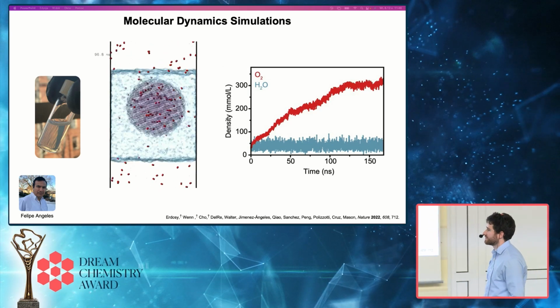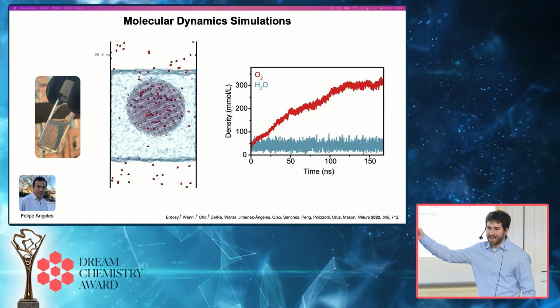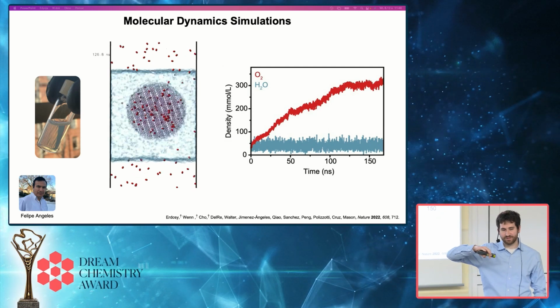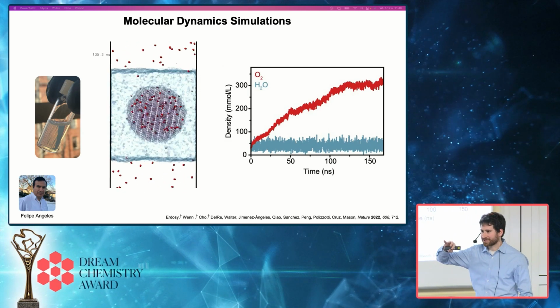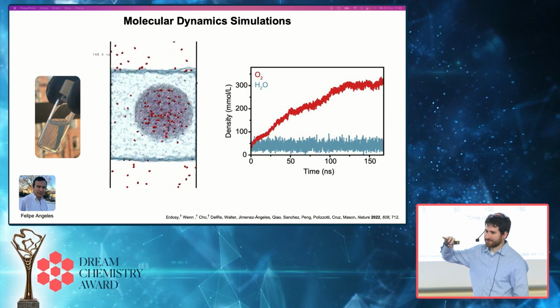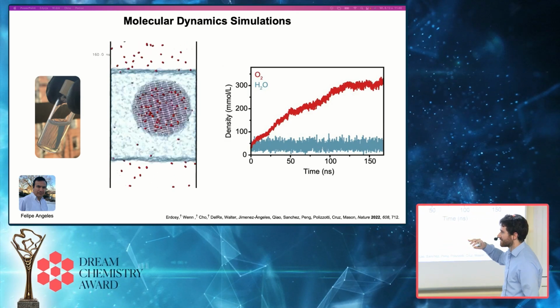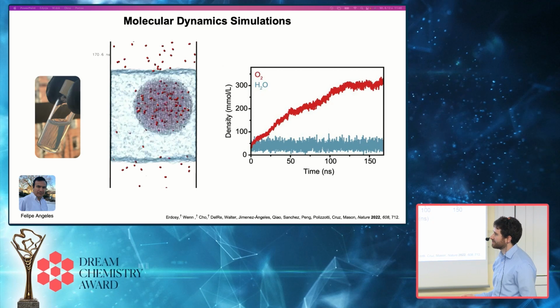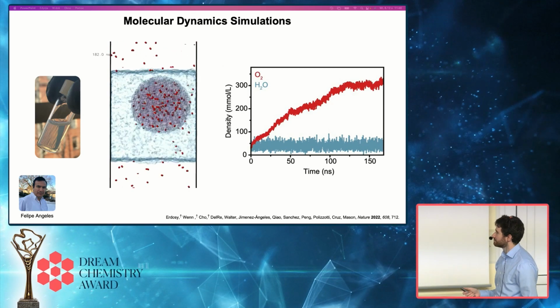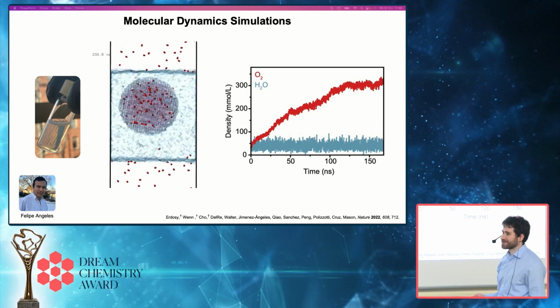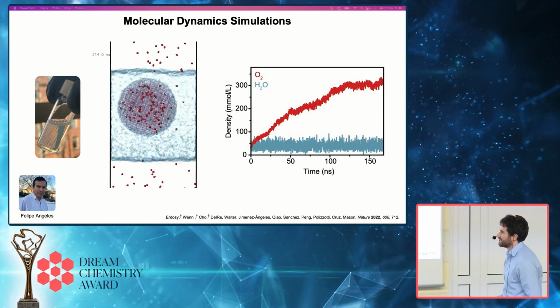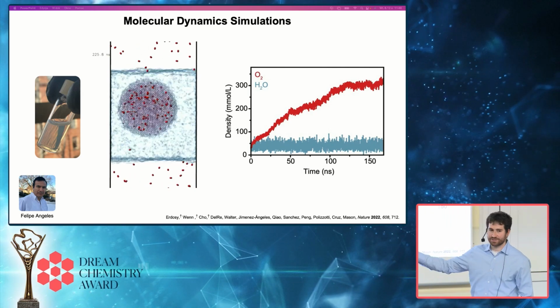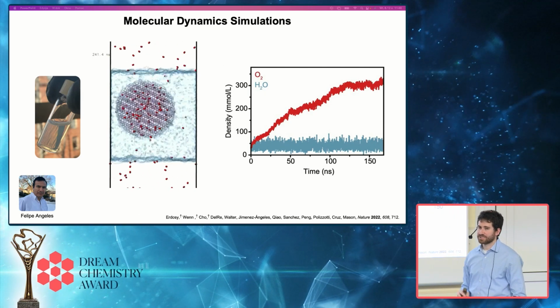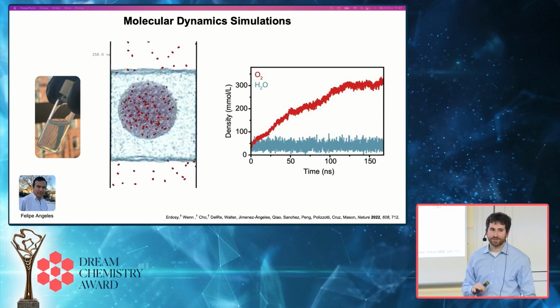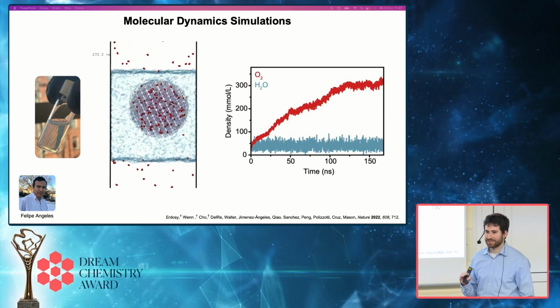What you can also see in the simulation is that the interactions of oxygen with the internal surfaces of the zeolite nanocrystal are extremely weak. So these are on the order of about 10 to 15 kilojoules per mole, about similar to a hydrogen bond. So these are very weak van der Waals interactions. So oxygen is rapidly diffusing within this material and rapidly exchanging with the surrounding aqueous environment. And so this is really important for evaluating the reversibility of gas storage within these materials.